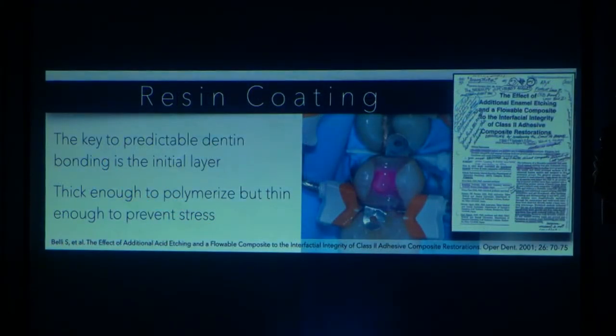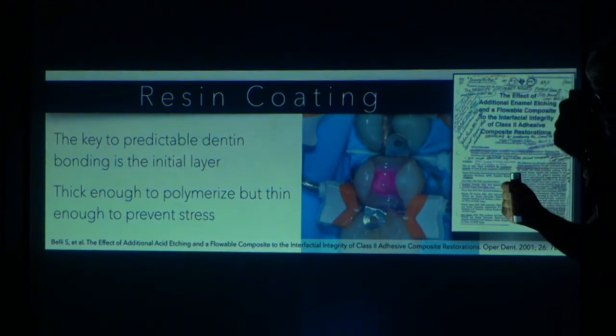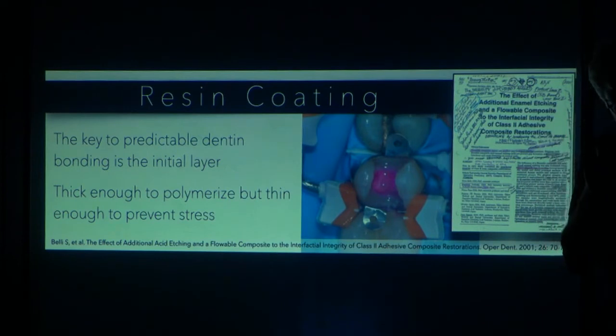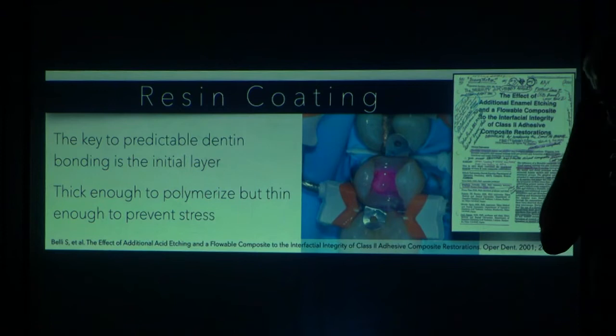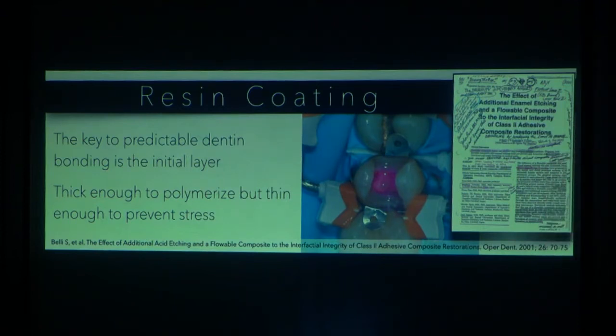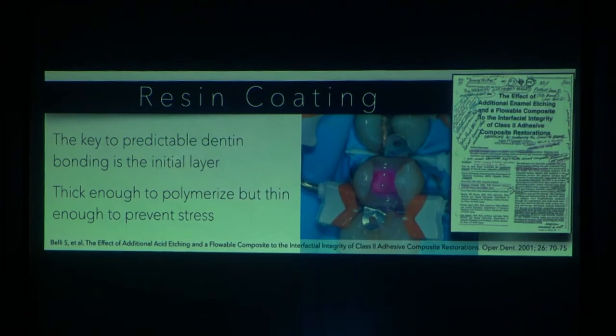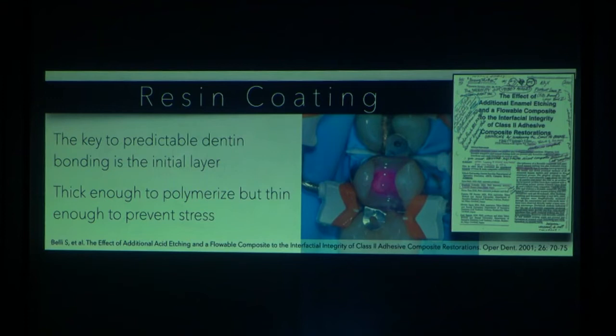So the key to predictable dentin bonding is that initial layer. It's got to be thick enough to polymerize. If you have an adhesive that is too thin, say 10 microns, which many of the bonding systems brag about, it works fine on enamel. But if you have a 10 micron layer of adhesive, it's totally air inhibited until you put the next layer of composite on that. What is air inhibition?